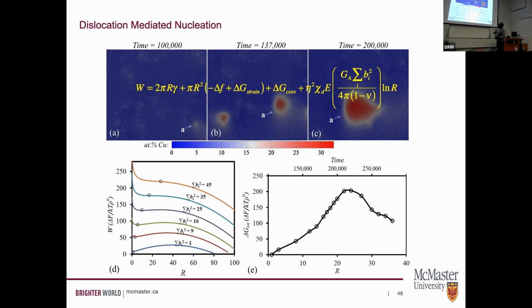So if you develop such a model, this term here is a measure of my dislocation, the Burgers vector. If I take a look at what the work of formation looks like as a function of how many dislocations, i.e. the Burgers vector, I find that with just a single dislocation, I have an energy barrier associated with my transformation. But as I add more and more dislocations, my energy barrier effectively disappears. So it seems like dislocations, or defects, are removing the barrier for nucleation of these precipitates. You could also track what the radius of this precipitate is doing, and you find that, yes, you do recover a critical radius that's also associated with this transformation.